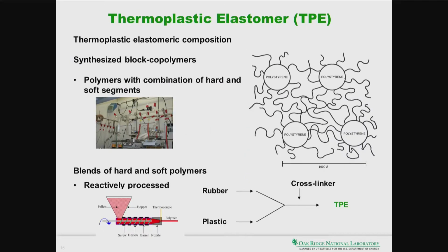Now, let me switch gears and talk about thermoplastic elastomeric material. On the screen, right-hand side, you can see a cartoon that shows a polystyrene domain and some soft segment. So these are the styrenic block copolymer structure in cartoon form. Polystyrene domains are the hard phase and soft segments are shown as flexible lines, and several polystyrene domains exist there. You may want to pay attention to the scale bar here, which shows 1000 angstrom, or 100 nanometer scale. So that means these hard and soft segments are well dispersed in domain form within a nanometer scale.